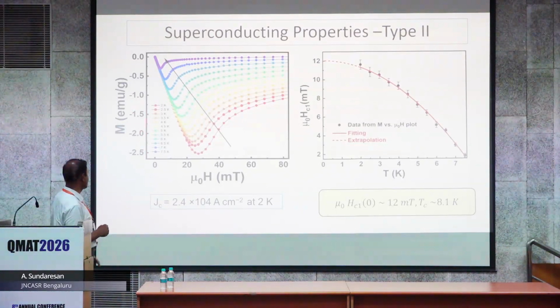So normal measurements at M versus H, to find out the JC value, and then to find out HC1, at various temperatures, using the same estimate. At HC1 at 0 field is 12 millitesla, and TC is 8.1, close to what is observed.